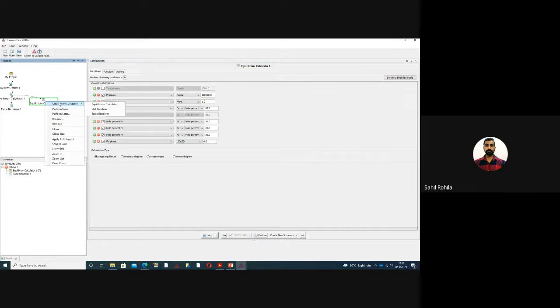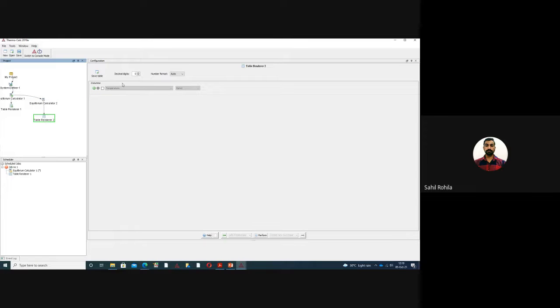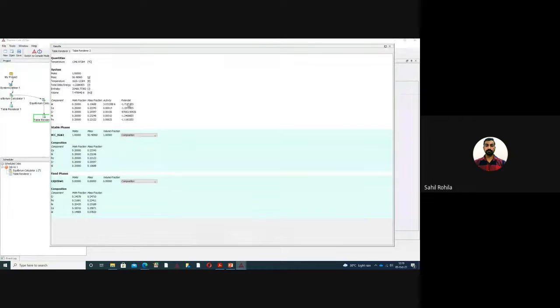I'll right click on it, create new successor, table render. I'll check the temperature, Celsius, perform, and it will give me the temperature. 1346.97 degrees centigrade is the solidus temperature of the high entropy alloy, and at that point the liquid fraction is 0 and the BCC fraction is 100%.